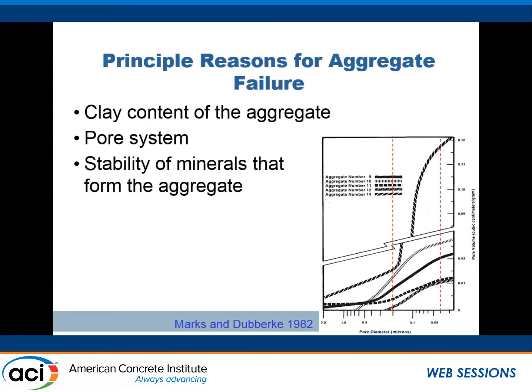Very small pores, the water doesn't get in at all. No problem, because if we haven't got the critical saturation that Tom referred to, we don't have an issue when freezing occurs. However, there is this range which is just wrong. And that range is in the order of about, I need to read the numbers again, it was about 0.04 to 0.2 micron. And this range is just wrong because capillary suction is high. It loves to pull the water in. But the thermodynamics is such that it's really difficult to get the water to evaporate out.